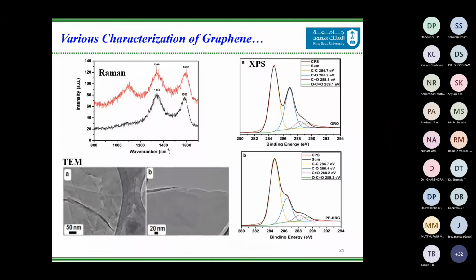Furthermore, we also carried out Raman spectroscopy, because Raman spectroscopy is a very important tool for layered material. For graphene, there are two main features that you observe, the G band and the D band, which are observed at 1575 per centimeter and 1350 per centimeter.